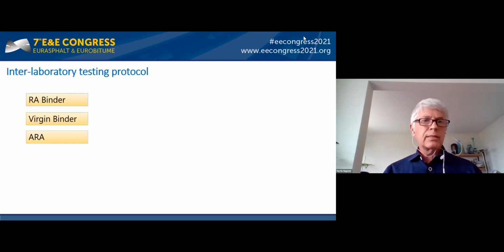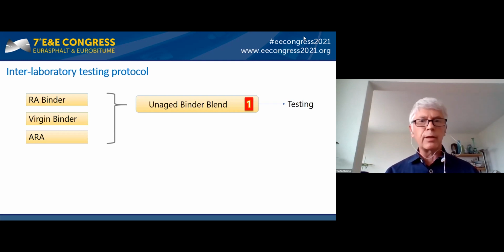So what did we do? First, we decided that we stay on the binder level, because when you go to the asphalt mix level, you have additional impact factors. So for the start, we wanted to make the impacts as little as possible. So what you need is actually a reclaimed asphalt binder, a virgin binder, and a small amount of ARA to produce a blend, which has more or less the same properties as a virgin binder you use in this case. Then you test it.